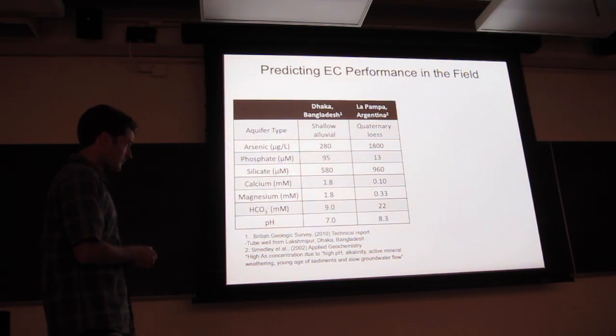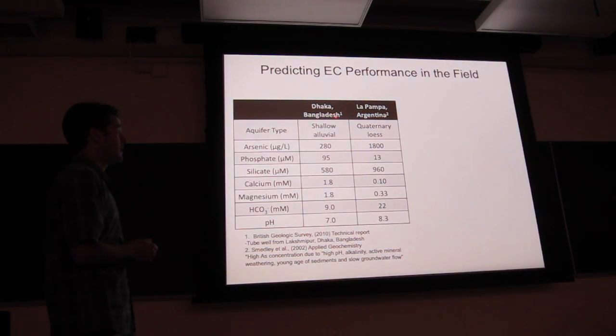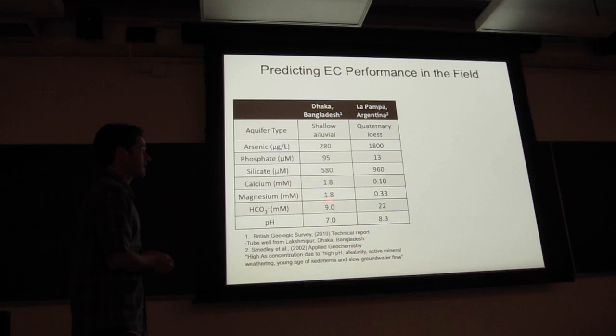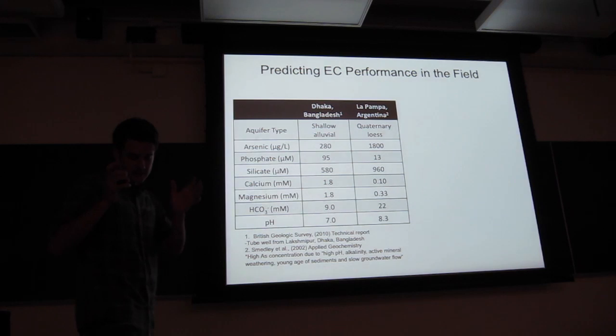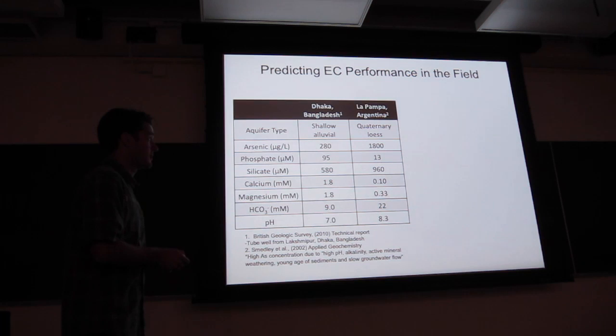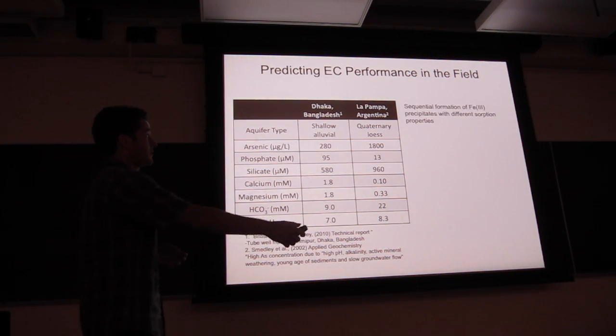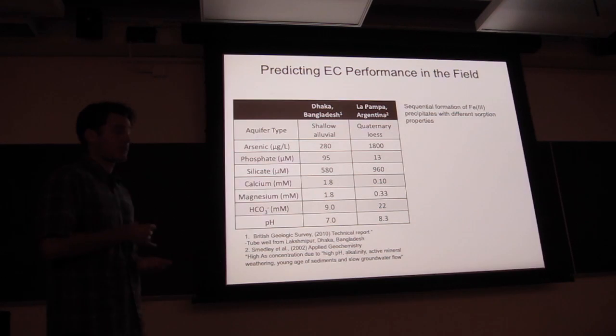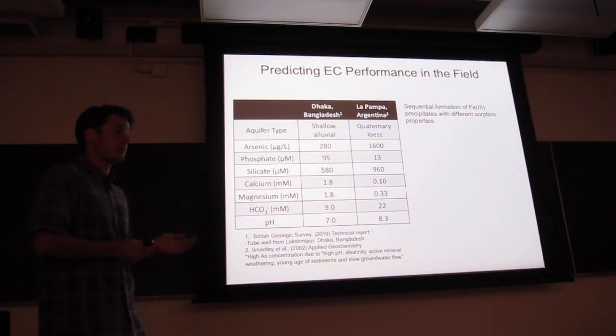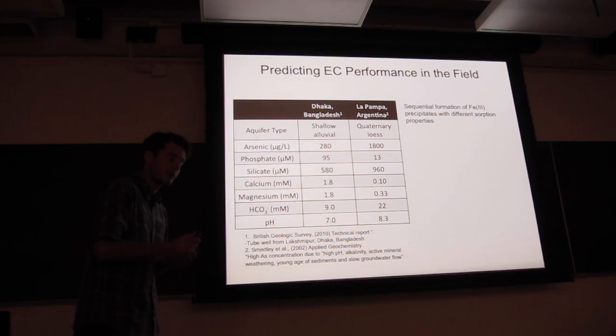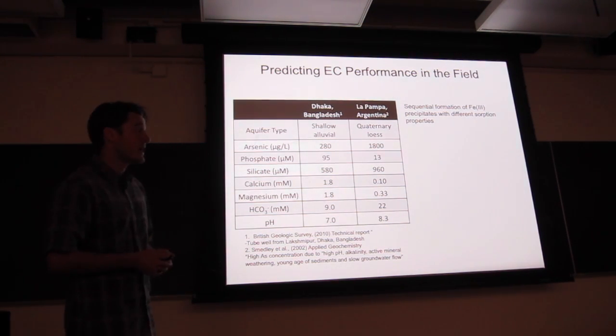And so I'm plotting an example of two different groundwater aquifers, and they have distinctly different groundwater compositions, especially with respect to these bivalent cations. So the aquifer in Bangladesh has a high concentration of calcium and magnesium, and the aquifer in Argentina has a lower concentration. And so we can begin to predict how EC is going to work in these electrolytes. So the first thing is that regardless of the presence or absence of calcium, the sequential formation of iron precipitates is going to be important. At the onset of electrolysis, we're going to generate particles that have a really high oxyanion to iron ratio.